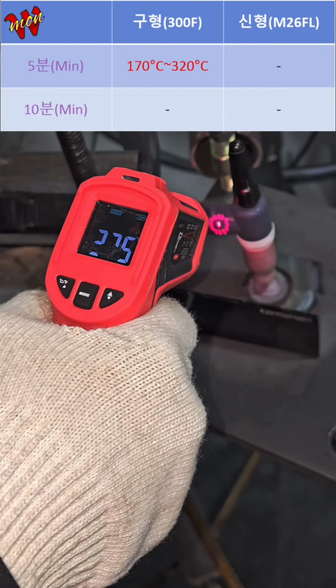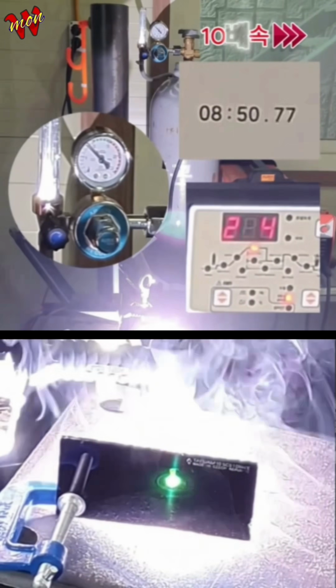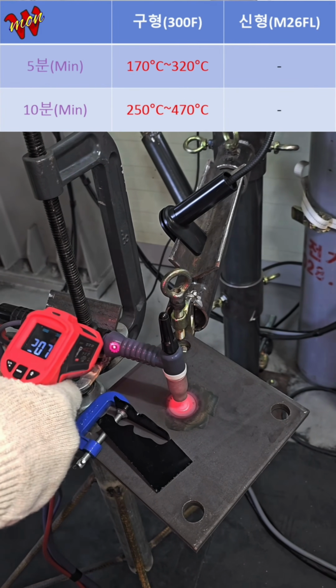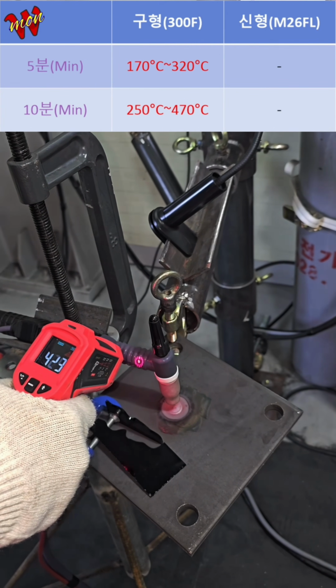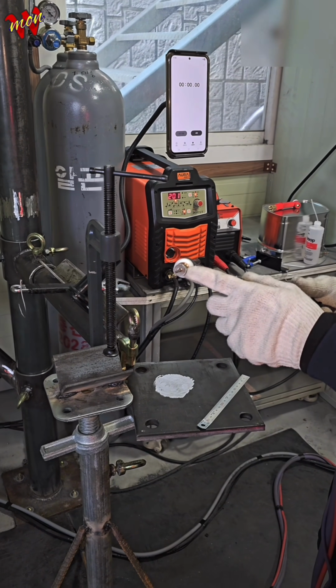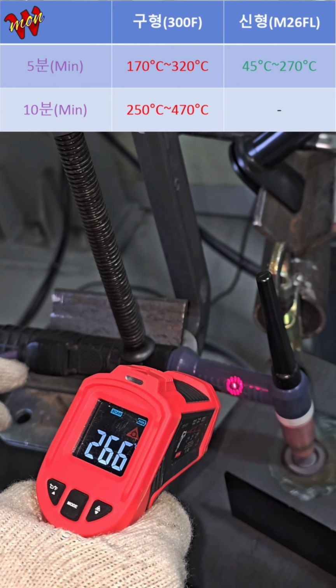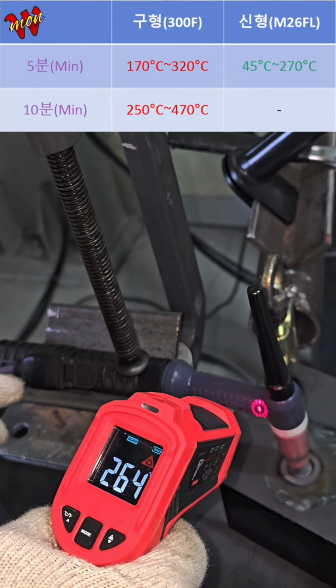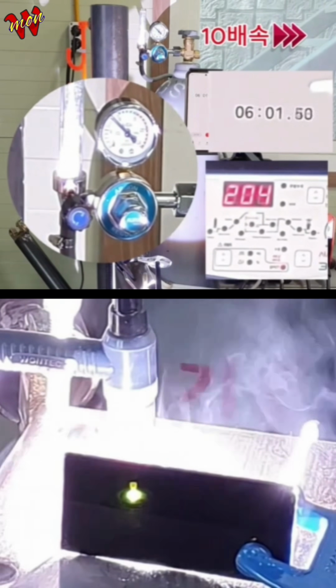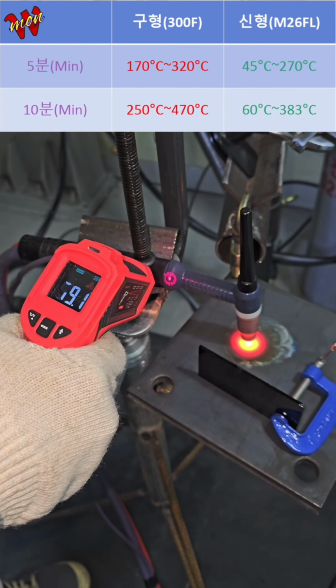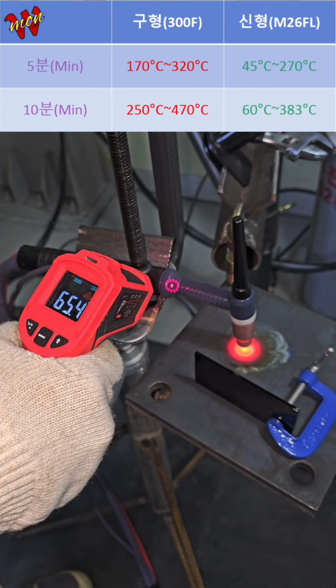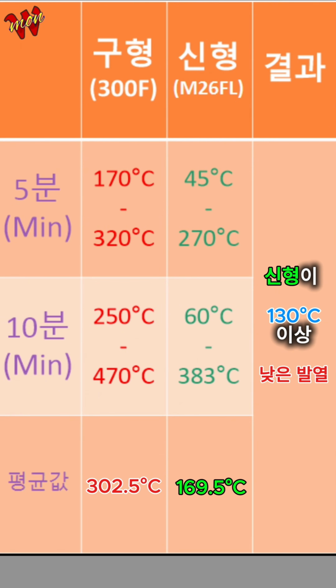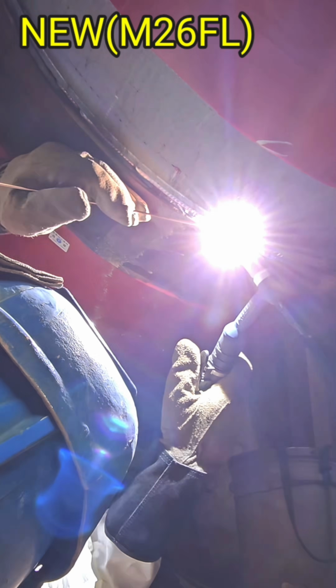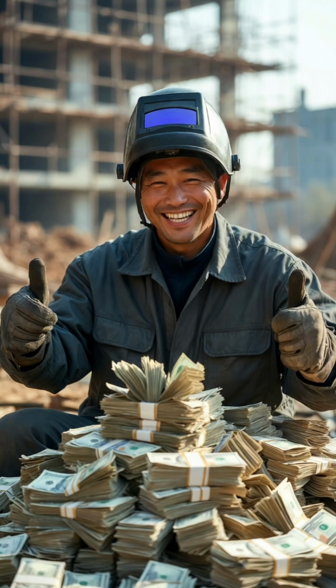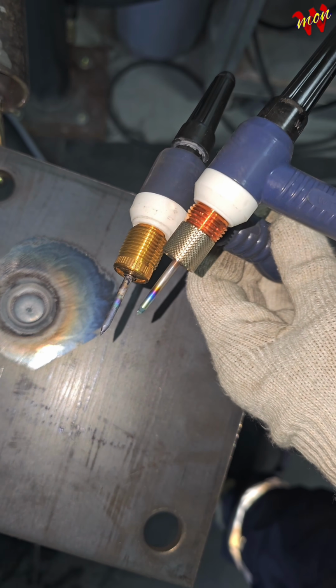Old 300F came in at 170 degrees Celsius on the low end, 470 degrees Celsius at the top. Brutal. New torch at the 5-minute mark, already running 100 degrees Celsius cooler. Easy. Final result at 10 minutes, 60 degrees Celsius to 380 degrees Celsius. Average of 130 degrees Celsius cooler than the old torch, not even close. The longer you run it, the more your efficiency and output are gonna climb. Here's the full 10-minute test results.